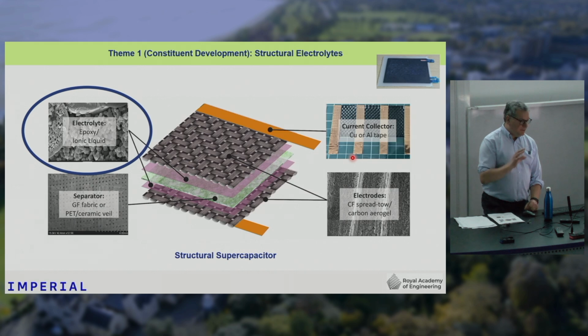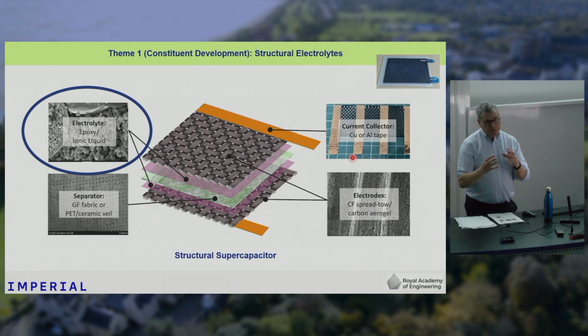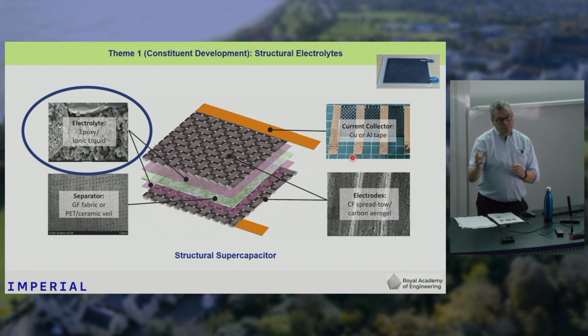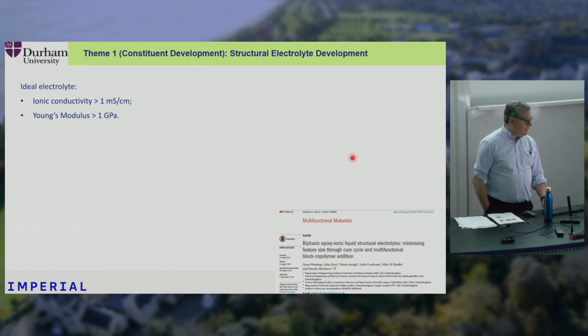With the electrolyte, this is more challenging because we want a material that's mechanically good. It's rigid, so it can carry mechanical loads. It can transfer loads between the fibers, but it's got to allow the ions to flow between the fibers. So conventionally, electrolytes are soft, they're liquids or even gels, and they allow ions to flow. If you have a rigid material, it's difficult for those ions to move. So the approach we've taken, and we have some aspirations in terms of performance we want to achieve: we want a Young's modulus of the electrolyte to be beyond a gigapascal, and we want the ionic conductivity to be beyond 1 millisiemens per centimetre.